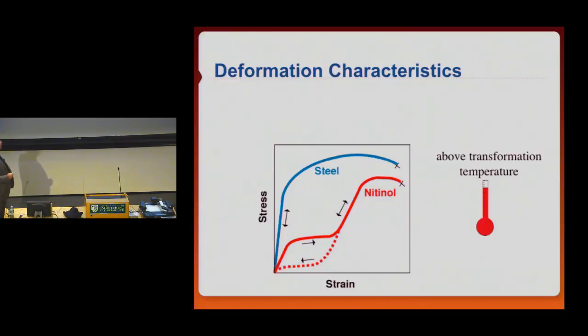So if we compare that with stainless, everybody knows stainless has a linear elastic range here, and then plastic deformation, everything from here to there is plastically deformed. If you would unload from here, you would have permanent deformation, or from here you have permanent deformation. On the other hand, nitinol has this hysteresis, and even after whatever 10% strain, you still get back to the starting point. Now, this is an alloy where we do the tensile test above the transformation temperature of the alloy.